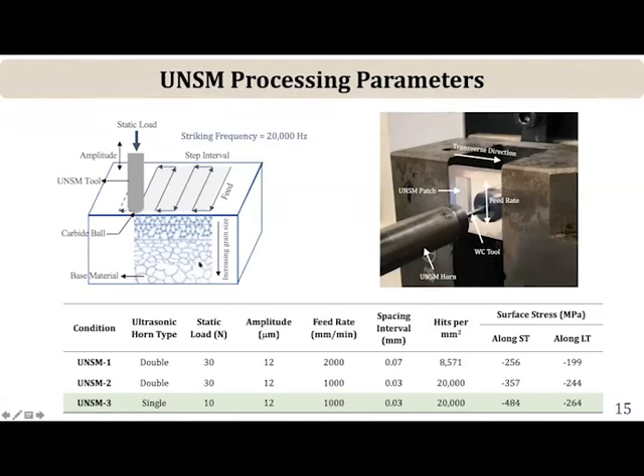Now one of the things with this technique is that just like in laser peening, wherever you're hitting, you're plastically deforming, the surrounding material wants to constrain that deformation, and you get compressive residual stresses. But the other important thing is, since it's a severe surface plastic deformation technique, you get surface nanocrystallization. Essentially, the grains get broken up into subgrains or crystallites, with high levels of misorientation and very high dislocation density, which also contributes to substantial hardening.